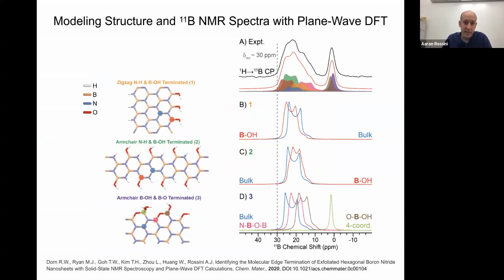We've also modeled the edges and calculated the boron NMR spectra. So basically what we think has happened is some hydrolysis of the edge has occurred. If we add an extra hydroxyl group to one of those boron sites that only had one hydroxyl group, that'll give us a 4-coordinate boron. Now that'll have negative charge. So then we just assume that it would be the other proton from the water that would be providing the charge balance. And this is a stable structure according to plane wave DFT, and that would give you a 4-coordinate peak that would explain the spectrum that we see experimentally.